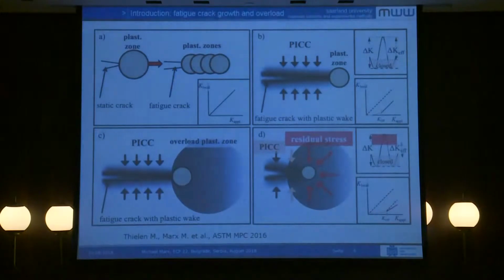Now, you may have some plasticity-induced crack closure, which means that the crack is closed in the unloading and in the beginning of the loading, and then this will change. You will have your applied K, but you will have the crack opening, the local acting K here at this K opening, and it will change a little bit. And now after the overload, you will have residual stresses in front of your crack tip, and this will change your loading because you will not reach the maximum K, because the maximum stress is now reduced, and therefore it will change your applied K and your local working K in this kind,